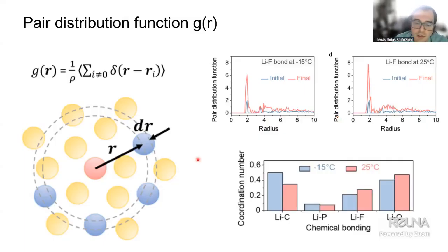And then in this bar chart over here, we can see the entire picture of lithium carbon, lithium phosphorus, lithium fluoride, and lithium oxide. At -15 it is mostly dominated by lithium carbon and slightly by lithium phosphorus, which tends to say that even though the objective of the project is to design a better electrolyte for a lower temperature, it's always going to be tough because the whole reaction is going to be governed by lithium carbon, which is not a favorable species to have in the SEI. At 25 degrees, there is going to be a higher presence of lithium fluoride, which is the most favorable species to have in an SEI.